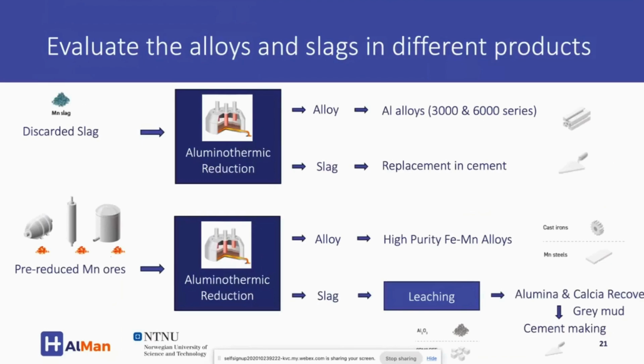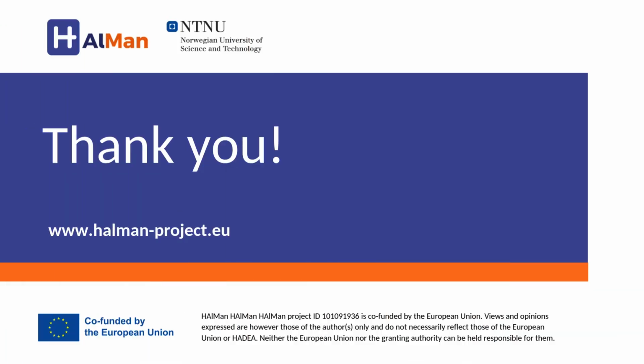And here you can see the process flow sheet. So the discarded slag that we use as a raw material, after the aluminothermic reduction, this slag contains quite a lot of silica. So it's not so good for hydrometallurgical treatment. So we test it directly in cement to see if it can be used there. And this alloy is then tested by the aluminium industry. And for the pre-reduced ores, there we produce an alloy for the steel industry, and the slag is leached and alumina is extracted, taken back to the aluminium industry, and we are extracting critical raw materials from this gray mud.